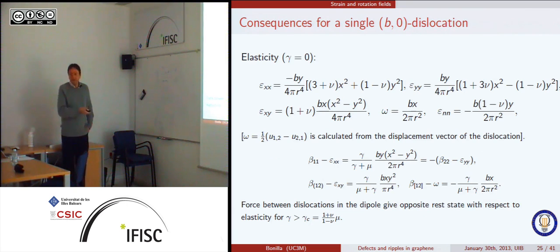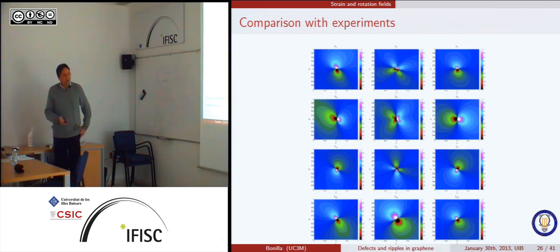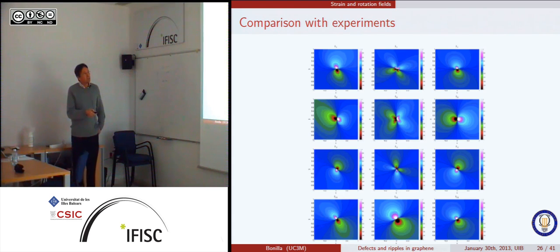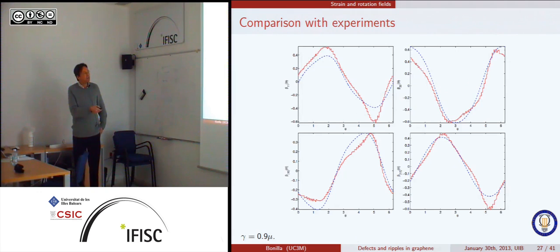So here, of course, I do not give you all the details, which are kind of bothersome. So this epsilon is the result of linear elasticity for the one dislocation directed about the x-axis. It gives you a rotation too, in classical elasticity. And this difference is the effect of the rotation energy. So you see that this is just as important as that. So what we found here is just that if we put the rotation modulus to be 90% of the shear modulus, you essentially map correctly the experimental data. Whereas without the rotation, you get classical elasticity, which is qualitatively different.